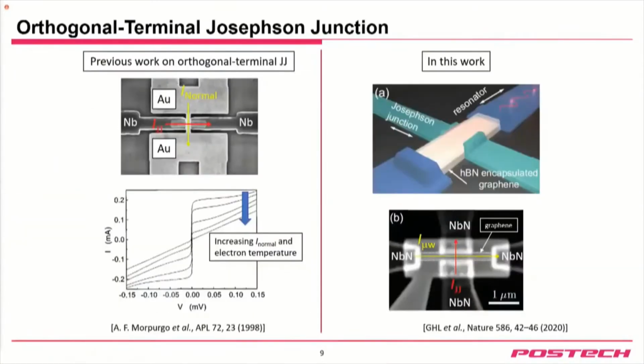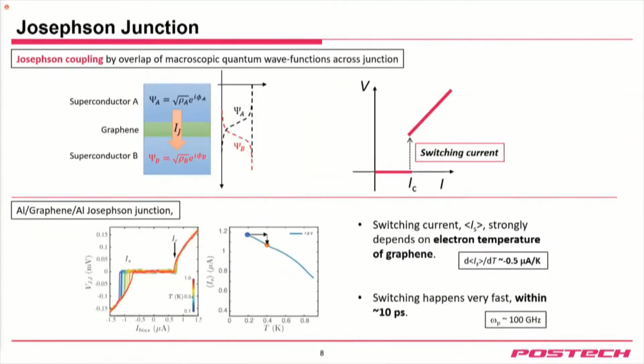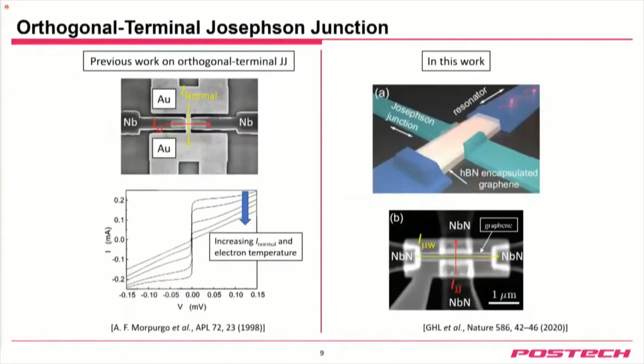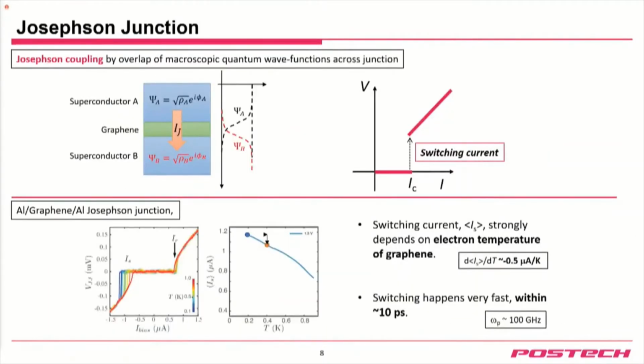But if any photon comes in and heats up the electron temperature from 200 millikelvin to 400 millikelvin, the IC will suddenly drop below 1.1 microamp. Now the bias current is above the critical current, so the Josephson junction will switch to a resistive state. Then we can detect the Josephson junction voltage. And the switching is very fast. It takes less than 10 picoseconds.